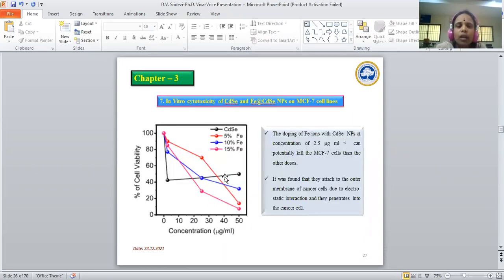In this slide, you can see the in vitro cytotoxicity of cadmium selenide and Fe doped cadmium selenide nanoparticles on MCF7 breast cancer cell lines. Initially, the cells were exposed at various concentrations such as 2.5, 25 and 50 microgram per ml. It was observed that the Fe doped cadmium selenide nanoparticles at low dose, that is 2.5 microgram per ml, can potentially kill the breast cancer cell lines better than the other doses. They attach to the outer membrane of cancer cells due to electrostatic interaction and penetrate into the cancer cells.